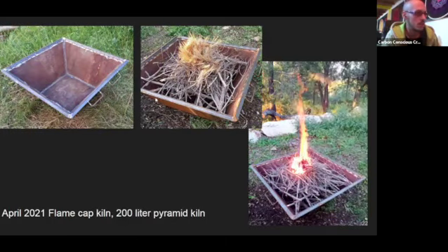So what I found is very helpful when starting a fire in a flame cap kiln is to create a grid about halfway up the kiln and light the fire on top of that, to allow a lot of oxygen flow at the beginning of the fire, because then it seems to get going much quicker, and there's less risk of being left with lots of unburned embers at the bottom of your kiln, which can happen if you start the fire directly on the bottom.